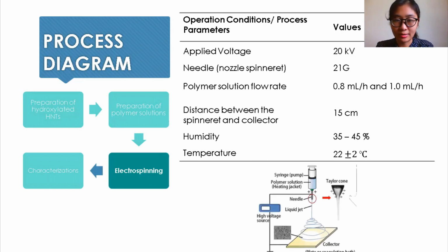So shown here is the setup in the vertical configuration. The electrified polymer solution travels from the needle tip to the collector plate with aluminum foil. The deposited fibrous mats were dried under atmospheric pressure at room temperature and carefully detached from the aluminum foil for